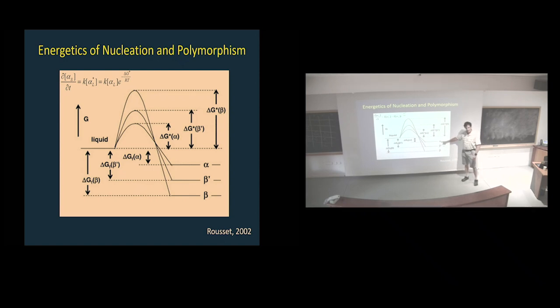Alpha, and then very slowly the fat goes, oh, I think I'm going to go to beta prime, and depending on the molecular structure, maybe I'm even going to go to beta. And then you get defects in chocolate: my form changed, now it doesn't melt in my mouth, it's waxy, or you get big crystals that have recrystallized into the beta form. It's a catastrophe. A margarine maker's nightmare is to go from the beta prime to the beta. So for a lot of people that crystallize fats, it is a story of controlling polymorphism, particularly chocolate. Chocolate is super critical.